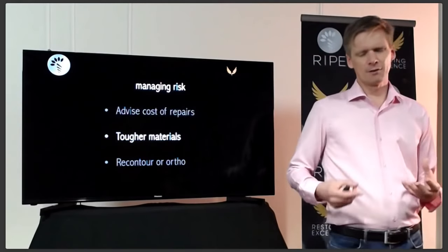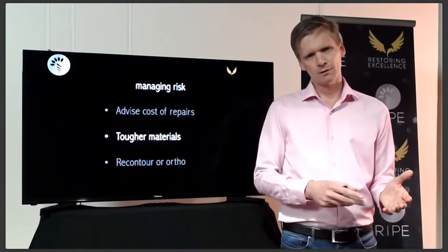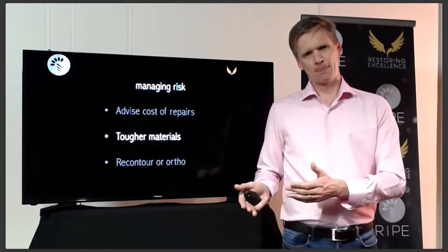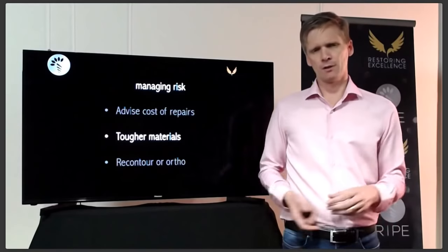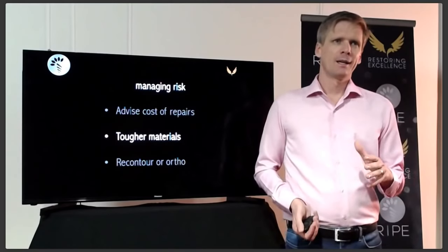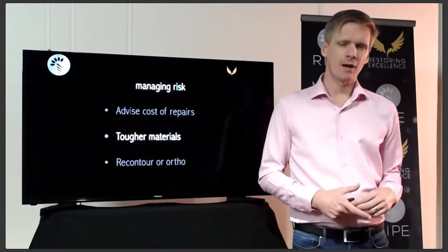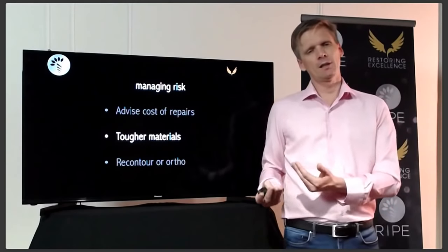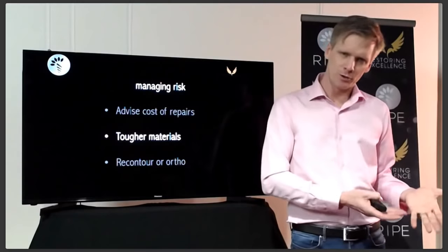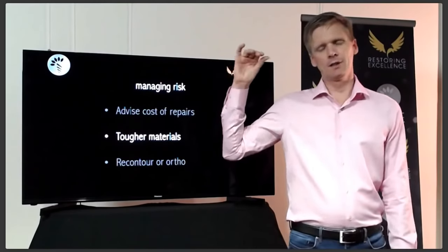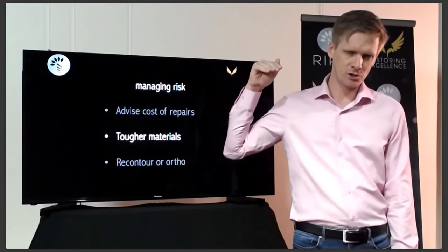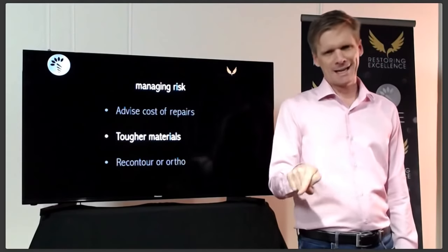We do have tougher materials, okay? Not stronger, but tougher, okay? Emax, lithium disilicate, is not the strongest material around, but it is very tough. It's resistant to fracture, okay? If we go to zirconia, it needs to be thick. So one of the problems we used to have was that we had porcelain fused to zirconia. You would get a crack in the overlying porcelain, which would create a massive stress concentration. It would travel down and hit the zirconia.